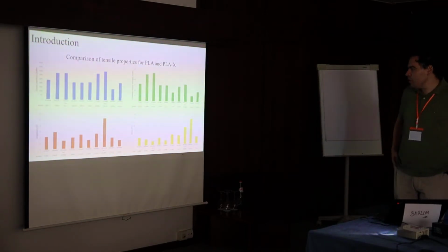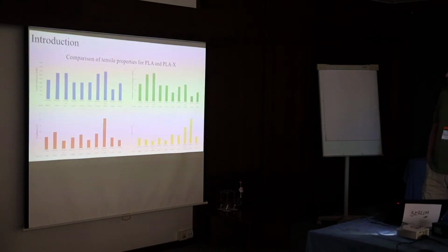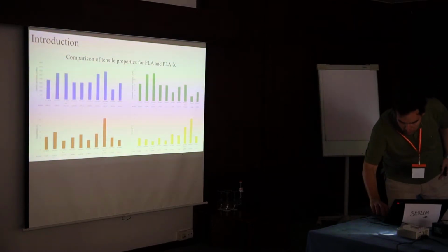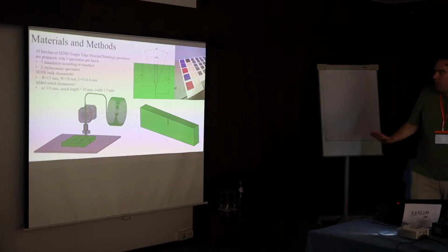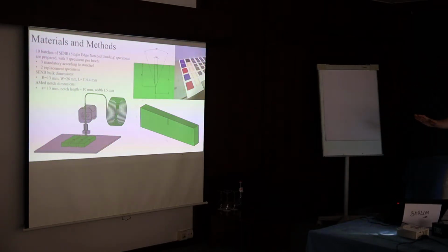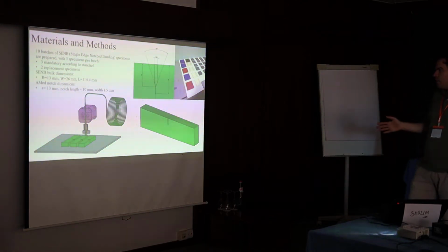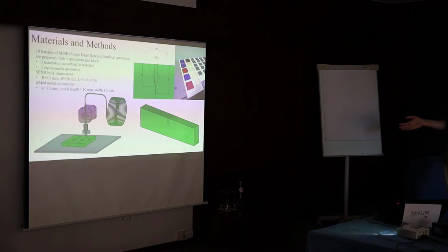Here are some results from the previous VCF conference concerning the tensile tests of PLA and PLAX, but you've seen the stress-strain diagrams, and that's mostly about them. So we created SENB specimens for fracture toughness assessment tests. We used 5 specimens, 3 were mandatory, 2 were used as a replacement.